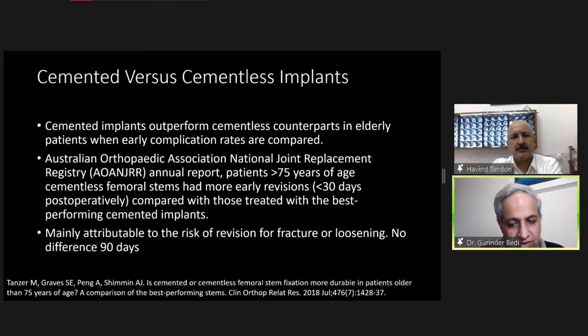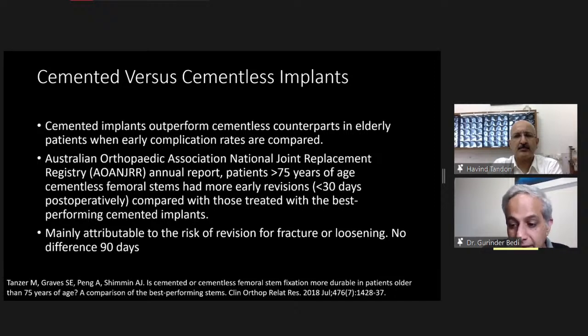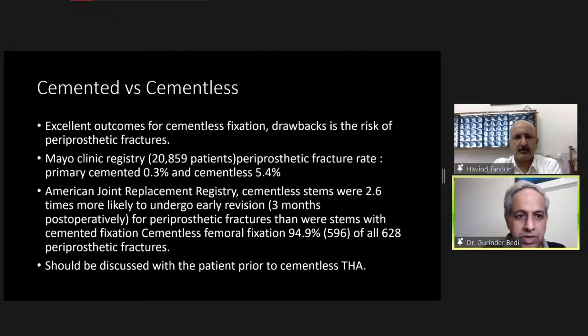In the Australian registry, it's for those greater than 70, 75 years of age. For early revision, cemented implants are doing much, much better, although after 3 months, the advantage is neutral. The major thing that happens is, one, the femur is fractured; second is early aseptic loosening, undetected early aseptic loosening. So excellent outcomes, yes, for cementless as well, but periprosthetic fractures remain a cause.